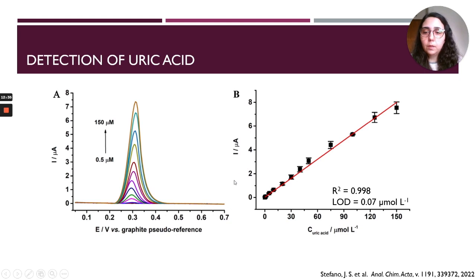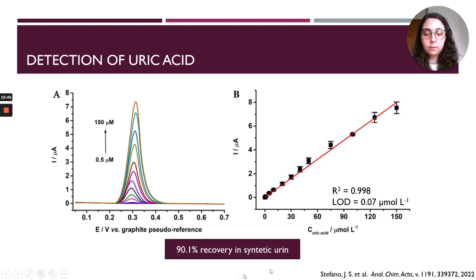Here's a calibration curve using DPV, so differential pulse voltammetry, from 0.5 micromolar to 150 micromolar. We got a very nice linear range with a limit of detection of 0.07 micromolar. This limit of detection would allow us to detect uric acid both in serum and in urine, and we did test the sensor in synthetic urine, which contains a bunch of organic molecules and a lot of salt, and we got around 90% of recovery, which shows that the sensor is also adequate for more complex environments.